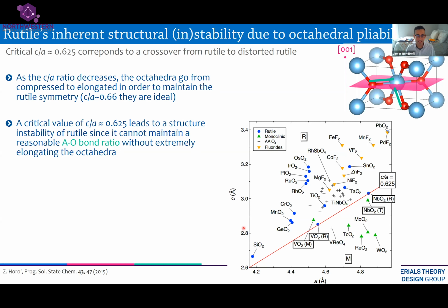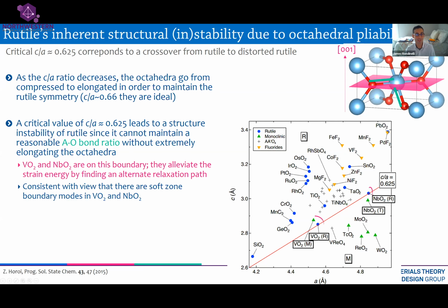If you're below this magic line of C over A equals 0.625, that's what this red line is here, then the compounds prefer to adopt the distorted structure, the one in which you saw where vanadium pairs up and forms pairs. And that can give rise or is conducive to then a metal insulator transition. And so what you want to do when designing this type of physical transition in this class of materials is you need to find a compound which lives somewhere along this line. And so that's the design challenge. So how do we get materials which live very close to this line? And if you look, niobium dioxide and vanadium dioxide are right there. And those are the two compounds in this family of rutile materials which exhibit the metal insulator transition. And so that's our design challenge.